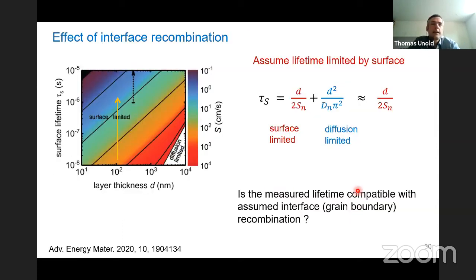Okay, so another aspect, of course, is you can check for consistency, as is the topic in this talk, if you look at the effects of interface recombination. So there is a relatively simple equation where you can calculate the lifetime due to interface recombination, if you assume only the interface limits your whole recombination in the device. And it's given by this equation here. It's two terms. One term is when diffusion doesn't really play a role, so the carriers are fast enough, and the second is the diffusion limited term.